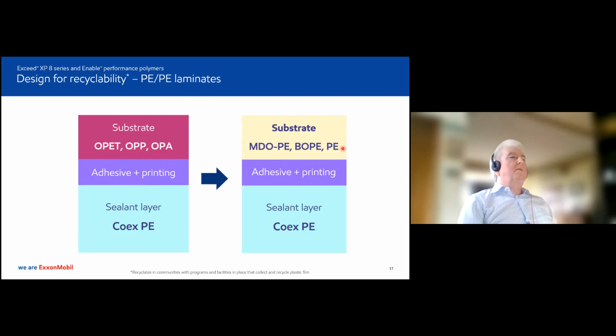Now, I've also included in this substrate just PE, in other words, unoriented PE. And the reason why that still has to be looked at is that there will be many customers that haven't invested in MDO lines, or obviously they don't have access to a BOPE line, which are far more expensive, and they're trying to make do with what they can. Now, this is very limiting, because when you have unoriented PE in your substrate, you get a much softer film, which is optically not so good, and you really do struggle with a decent overall laminate. But there will be some applications where it will be successful. The focus now that I'm going to talk about really is on the MDO part.